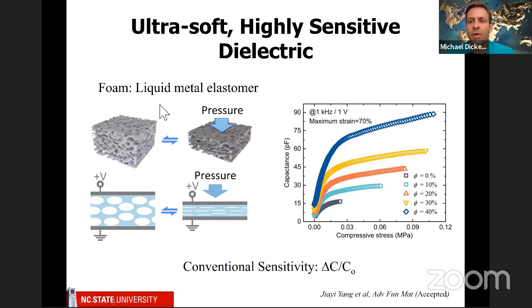We take the liquid metal elastomer, so liquid metal droplets mixed in with silicone. We make a foam out of it. And when you squish it, you increase the dielectric constant because you're displacing air. This is similar to the Bao concept. And what you'll see is that the capacitance, which is the thing you're going to measure as a function of stress, increases. It increases initially because you're displacing the air that's in the foam. So imagine squeezing a sponge or something like that. But then once all the air is gone, the slope changes and it doesn't work quite as well.